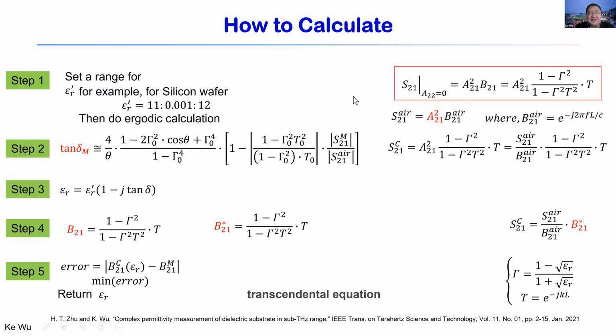So the detail of that actually involves several things. First of all, we basically use a perturbation technique. What do we do? First of all, we assume that all those previous equations, even with the material under test in the computation domain, are without loss. This lossless calculation can be denoted by this gamma with the subscript 0. This T0 means the lossless material under test. Actually, it's not test, it's the computation aspect.